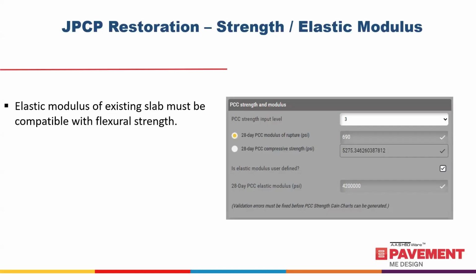In this case here, you've got an existing pavement, so you have to estimate things, what they were originally. And so you can do a core, break it, get an estimate of compressive strength, and then try backcasting that to what the 28-day strength would have been. And then obviously for the elastic modulus, you could also do a back calculation estimate from FWD and get that number. But it's important to make sure that, I guess I should have included a curve here to show you the relationship between flexural strength and modulus, how if you go above or below that line, you're going to either increase or decrease cracking.